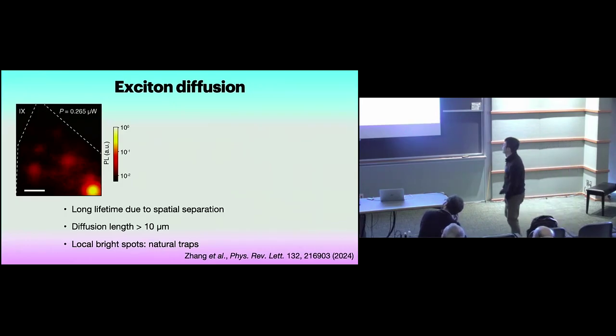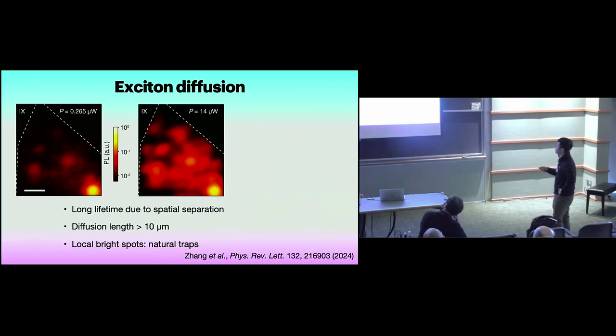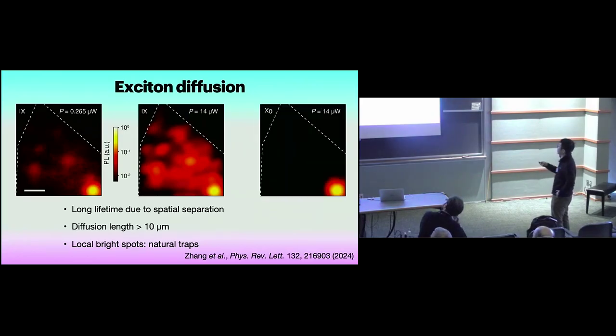This makes sense because interlayer exciton can have long lifetime, so even though you generate it locally, it can diffuse to a different region. If I increase the pumping power, the diffusion length becomes larger, and I see other area lights up as well. Compared with intralayer exciton, I see no diffusion at all.